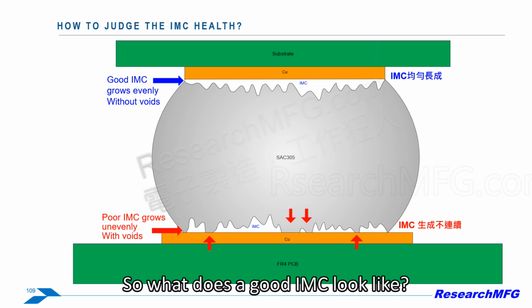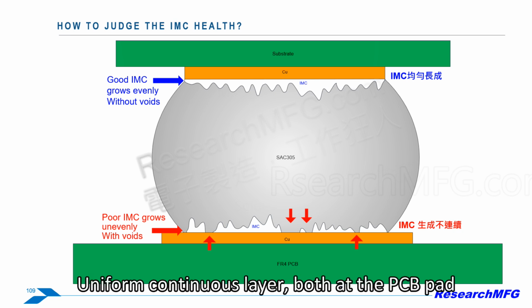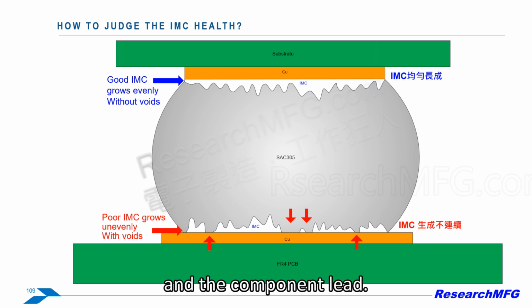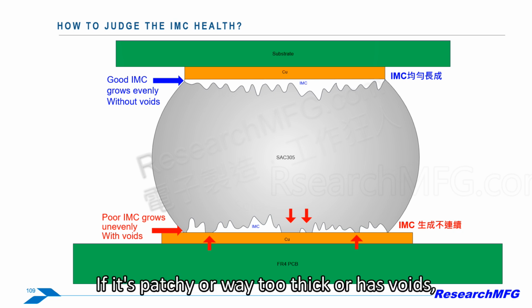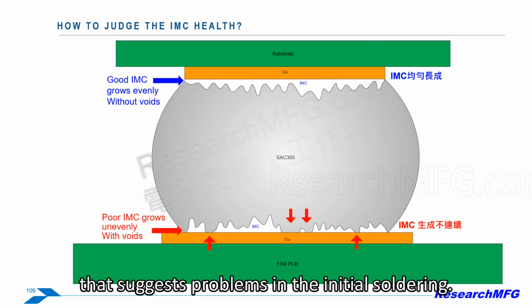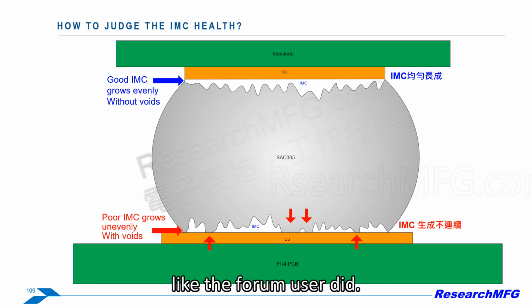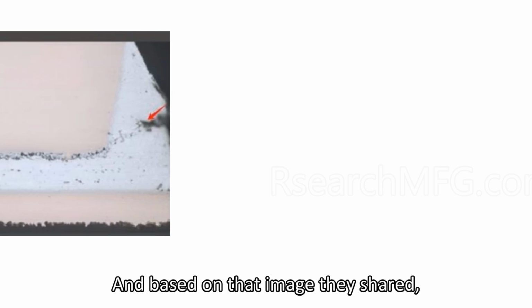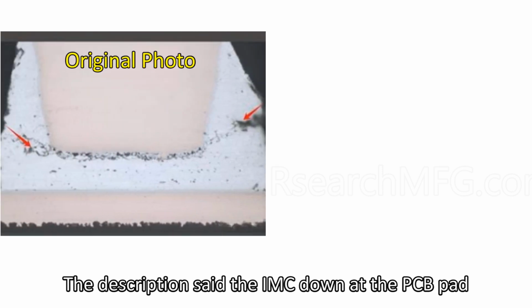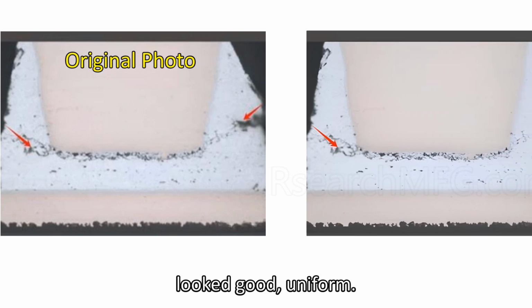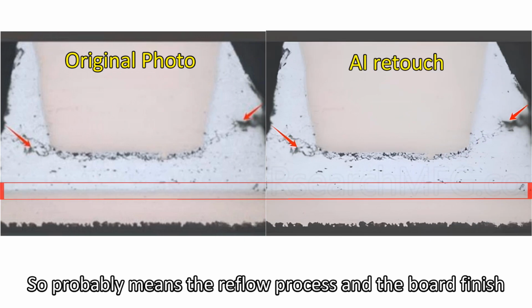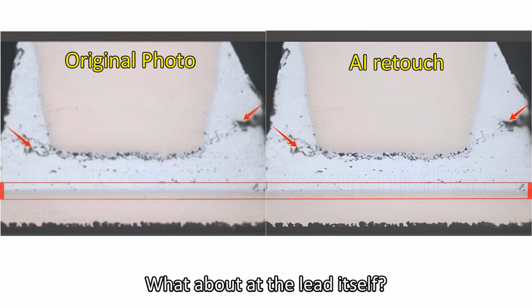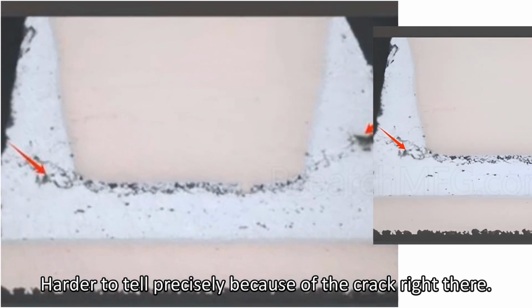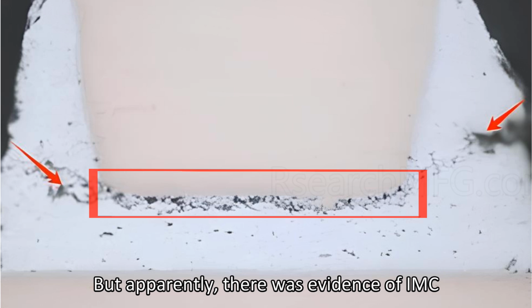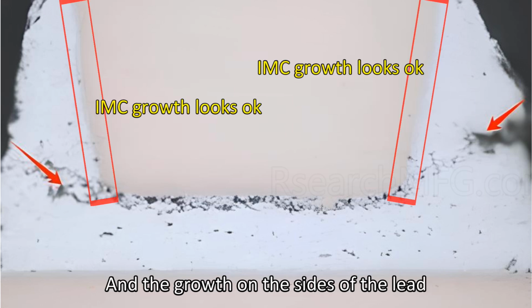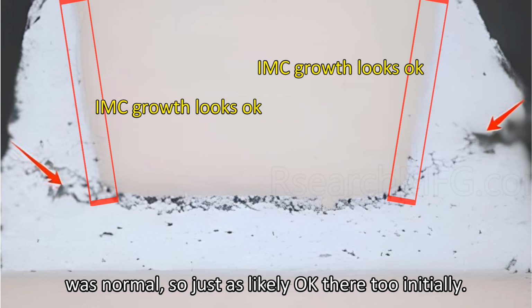So what does a good IMC look like? Uniform continuous layer, both at the PCB pad and the component lead. If it's patchy or way too thick or has voids, that suggests problems in the initial soldering. But you usually need to cross-section to see it properly, like the forum user did. Right. And based on that image they shared, what did the IMC look like in this case? Well, the description said the IMC down at the PCB pad looked good, uniform. So probably means the reflow process and the board finish were okay. Okay. What about at the lead itself? Harder to tell, precisely because of the crack right there. Yeah. But apparently there was evidence of IMC at the base of the lead, and the growth on the sides of the lead looked normal.